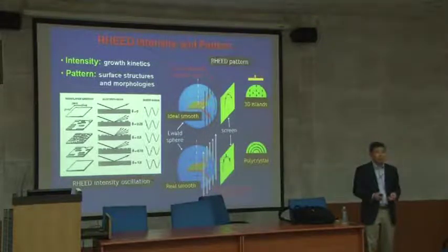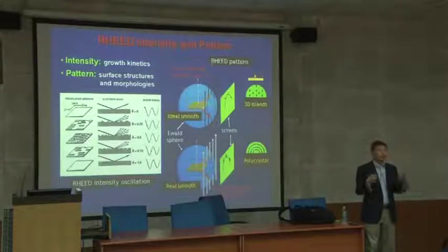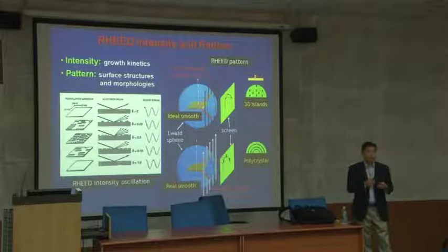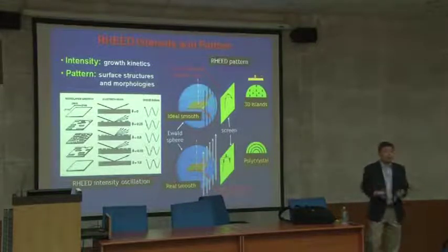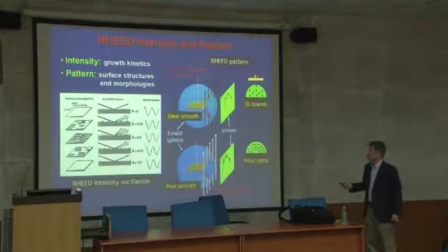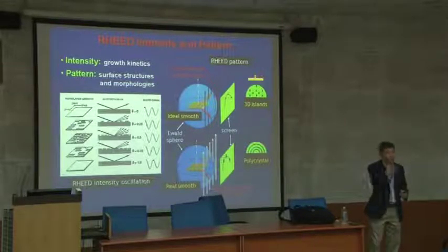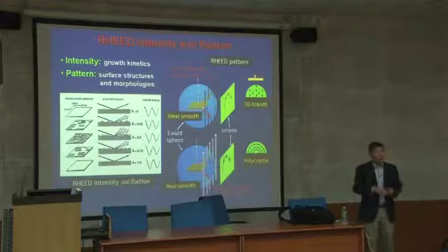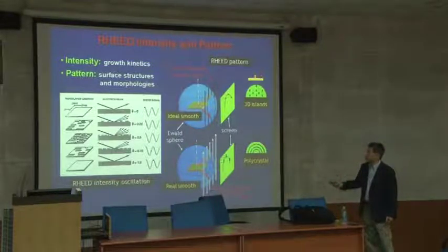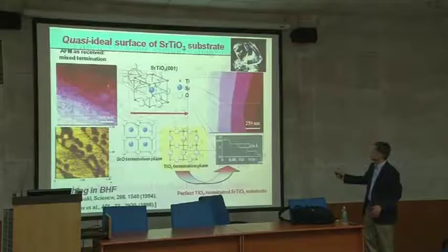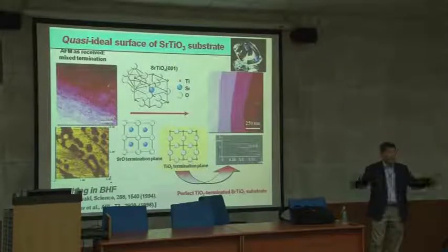Which one can you use? X-ray is one way to do it, but imagine that's quite deep. And then you can use the electron beam. High energy electrons, roughly 20 or 30 or 40 keV, and you can calculate the wavelength of the electron beam. That's a sub-angstrom wavelength, and that's why you can make atomic imaging with a transmission electron microscope. That wavelength can really see the atoms on the surface, the difference atoms make. So the electron beam is scattered the same way if the surface is flat, like this, with no atoms attached.